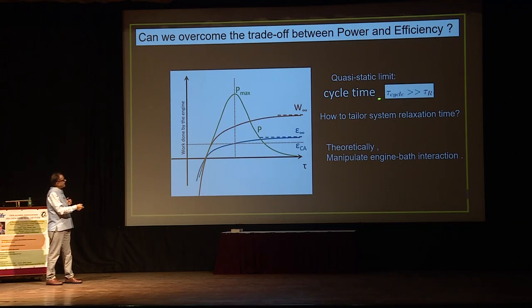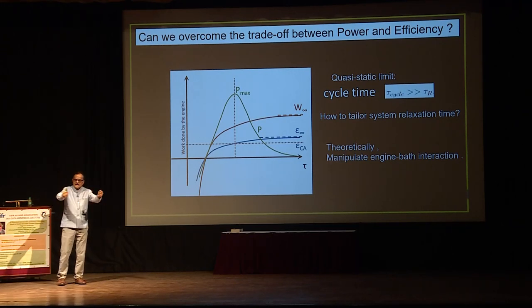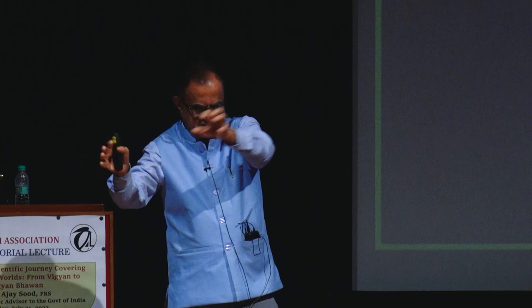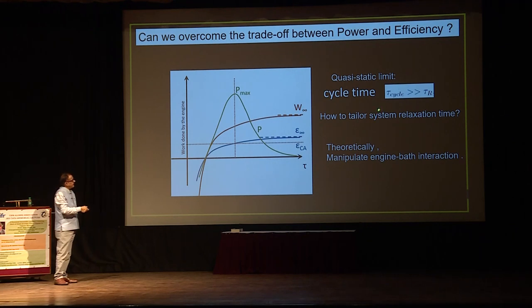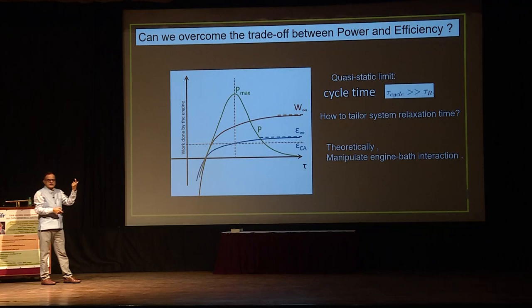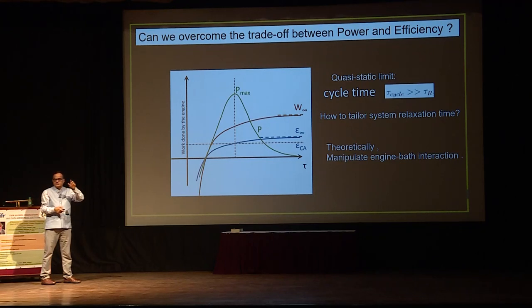Because if the cycle time is much, much more than any relaxation time, because there is a finite time when the engine and the reservoir will exchange heat, right? Because of thermal conductivity in a macroscopic system. As long as this is satisfied, you will have the quasi-static limit. In the last bacterial experiment, our cycle time was 22 seconds.